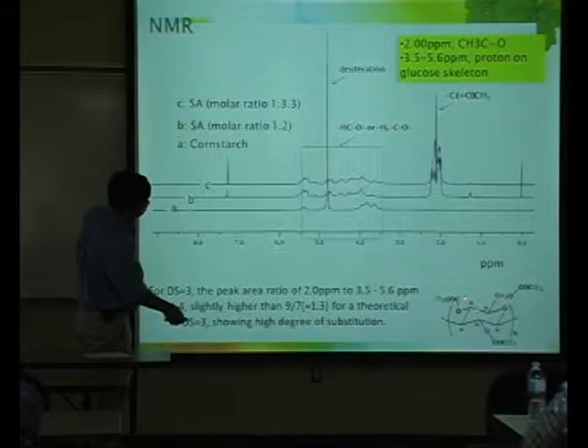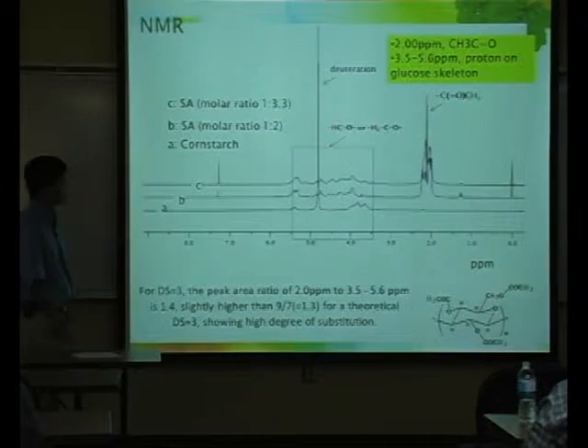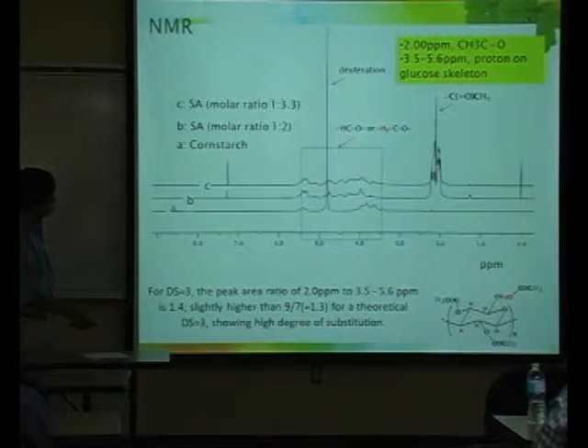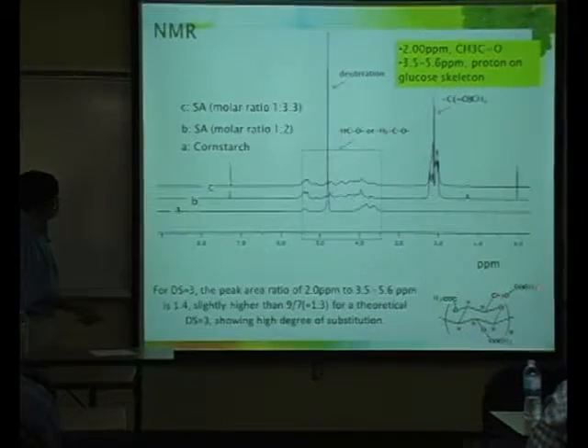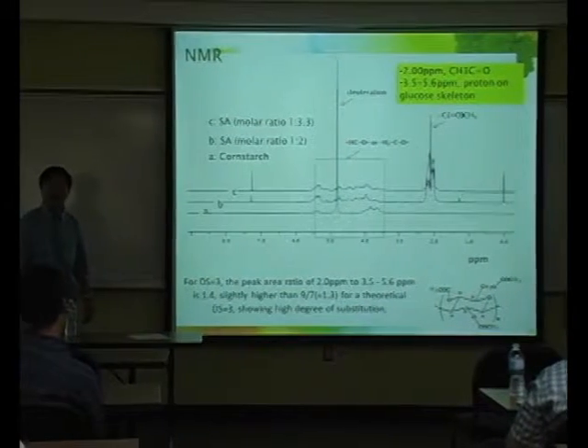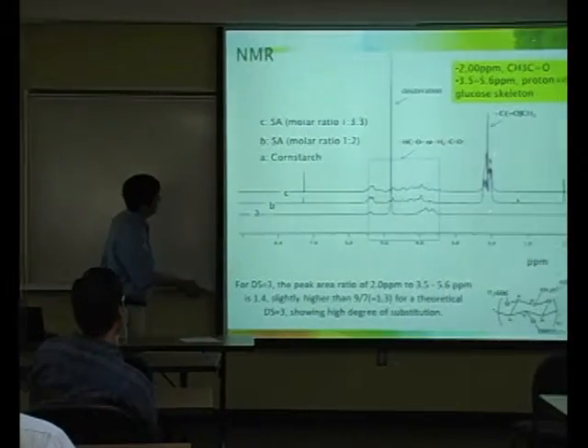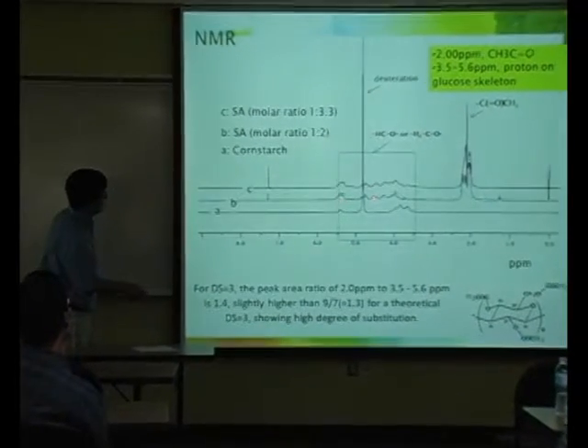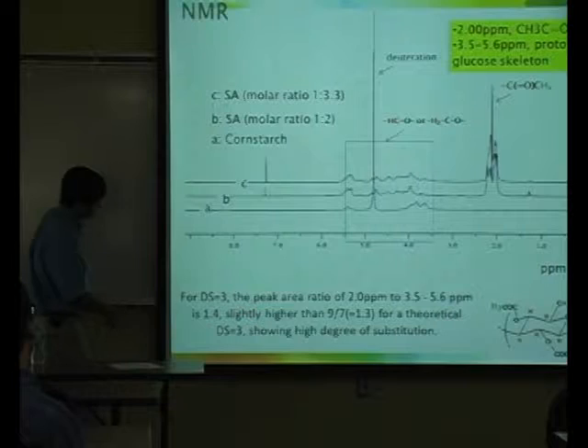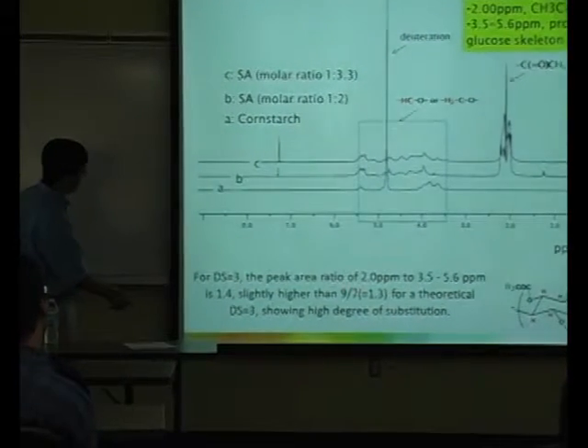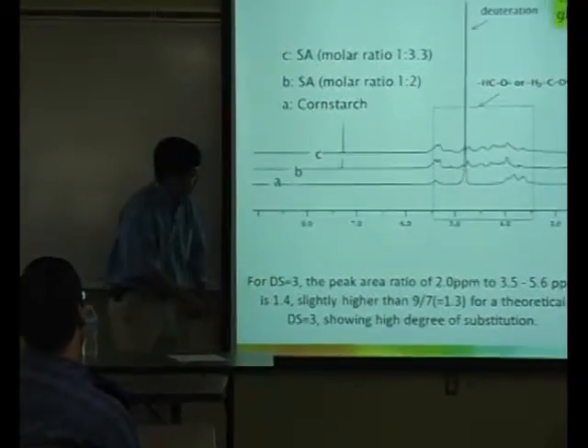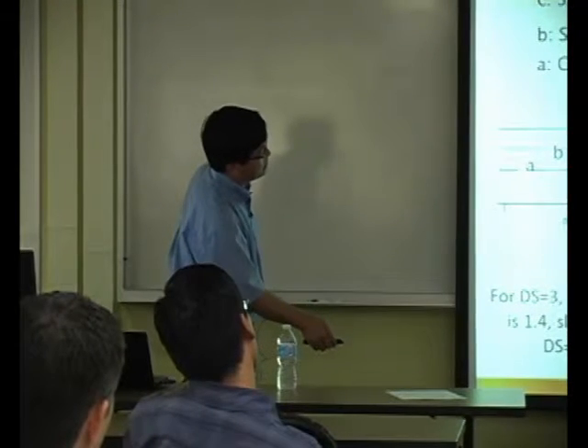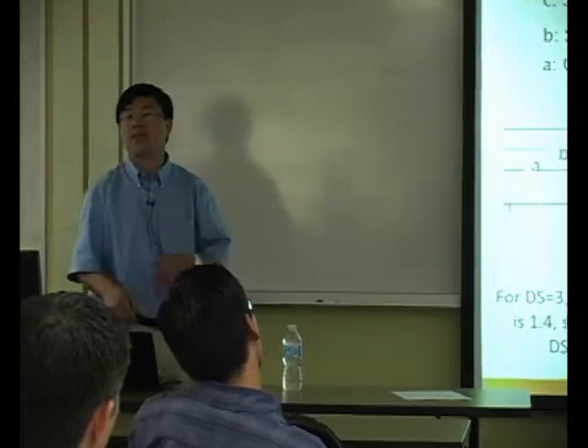And the other protons are on the skeleton of the glucose. So we can count the total number of H, the 7 in red color, and the non-ester H in green color. We can calculate the percentage by integration: the area under this region and the area under this region of the spectrum, we integrate and take the ratio. The ratio is about 1.4, slightly higher than the theoretical ratio, which means that all the OH is gone, all the OH functional groups replaced by ester. So the degree of substitution is 3, as expected. That's the proof of this product.